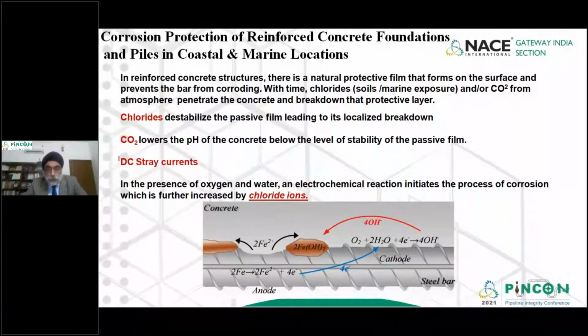So the design engineers should be aware that while you are trying to protect the buried steel piping, or trying to protect the tank bottoms of large storage tanks, we can cause stray current corrosion on nearby concrete structures, leading to a rapid deterioration of these structures. So these three factors should be kept in mind while ensuring that the steel rebars do not corrode, and to ensure the long-term integrity of concrete structures in a refinery or in a petrochemical environment.